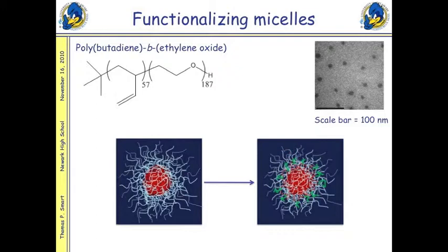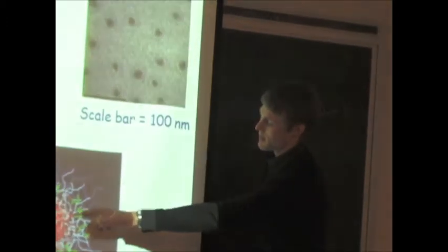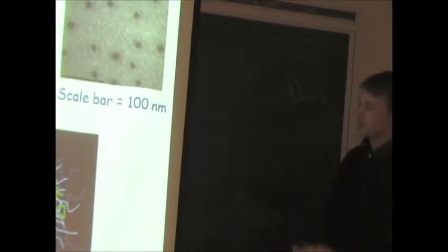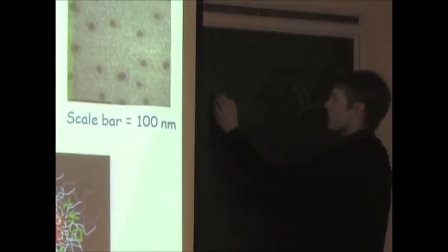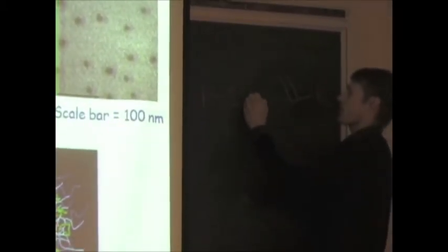So with this double bond, we've got that attached to our micelle, these sticking out all over. And what we're going to synthesize is these short sequences of peptides, effectively a miniature protein. But we're going to make them with a specific cysteine amino acid on the end, so our peptide sequence ends with an SH group, the thiol.